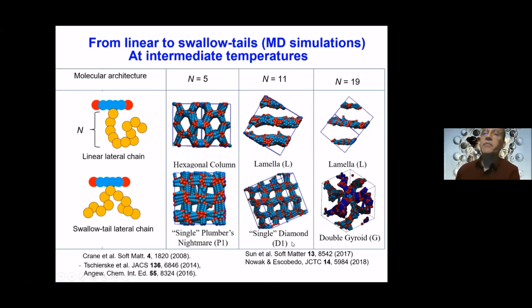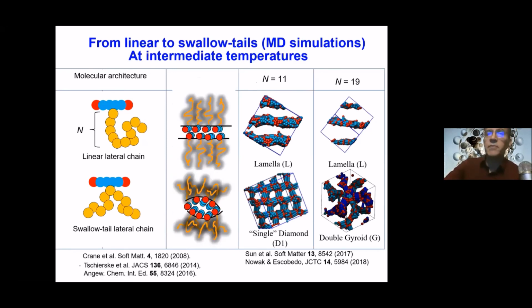But the key question would be, why is it that such a big difference, given this small change? One of the explanations is physical in nature. It goes as follows: if you look at these cases where the lamellar phase forms, the rods are packing into these layers, and the chains are going to extend to fill up this sort of rectangular volume. And if you make n larger, they can just extend farther into that region.